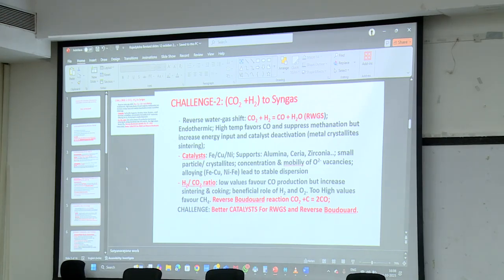Alloying the metal, with nickel or other metals, stabilizes the metal dispersion. See, there are two components. One is the metal, the other is the support. The role of the support is to adsorb carbon dioxide and retain one oxygen, because CO2 goes into the oxygen vacancy, and then CO comes out. The hydrogen plays a role in the reduction of the metal between different oxidation states, and also in supplying hydrogen to oxygen. The O2 minus vacancies combine with H plus to give hydroxyl groups. Hydroxyl groups combine to give water. So both the support and the metal are critical.